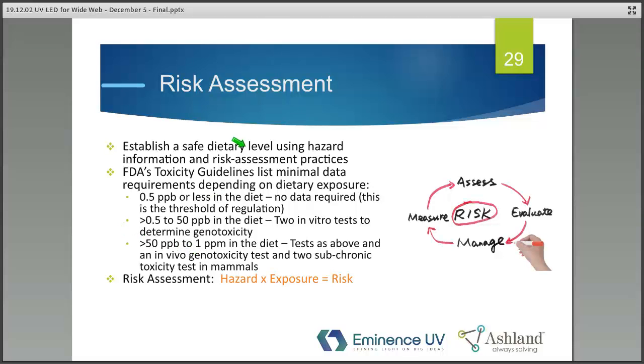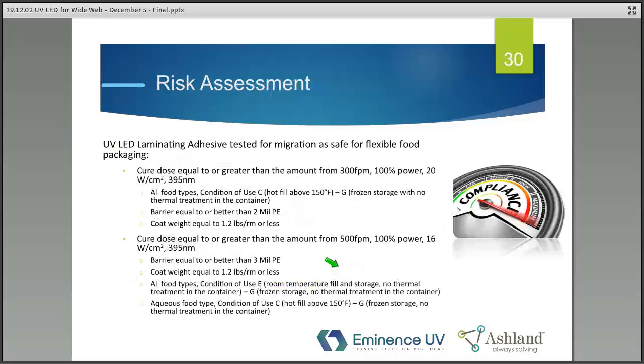So between establishing the hazard information from the tox data, you find the exposure, and the FDA has guidance out there as far as how you would look at exposure based on the type of packaging. They're called consumption factors. Between those two, you could determine the risk of the material. So using these principles, Ashland actually took two LED products and wanted to determine the migration of them. We actually did migration testing, and we were able to clear 2 materials.